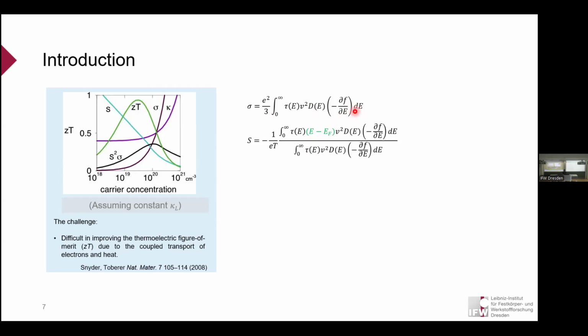That's why we need a band gap, because we can minimize the carriers from one side of the Fermi level, so we can ensure that the Seebeck is high enough. If we take the multiplication of the electronic density of states times the energy derivative of the Fermi distribution function, we get something termed the transport window. In the regular doping process, you are adding or removing electrons from the top of this window, and by doing that you follow these trends exactly. You get a limited value of ZT, and it's very difficult to boost it further.